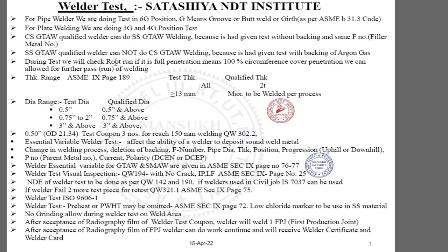During the test we check the root run welding. If the root is full penetration — meaning 100% circumference coverage with good penetration — we allow the welder to continue for further passes: hot pass, fill-up, and final capping. First we check the root; if penetration is good all over the circumference area, we allow the welder for the next welding pass.